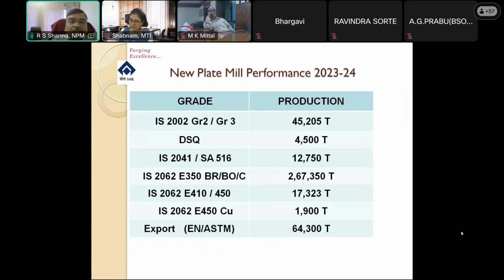In 23-24, the major grades which we supplied are grade 2 and grade 3. Boiler is only 45,000; earlier we used to cross more than 1 lakh in a year. In 21-22, we crossed that figure. DSQ 4,500, IS 2041 12,000, then 350 BR B0 and C 2,67,000, 450 17,000, and 450 BR copper 1,900. Then export 64,000.